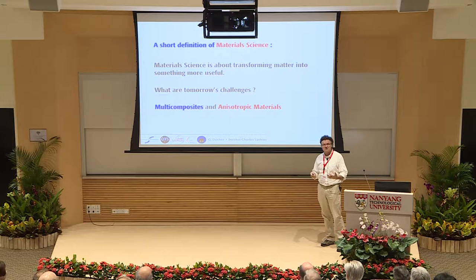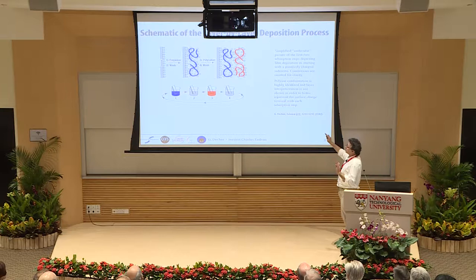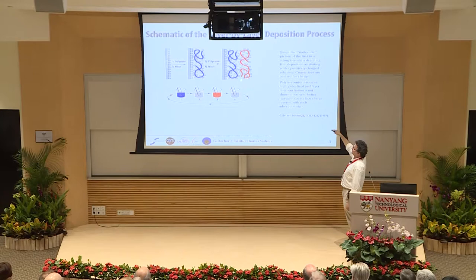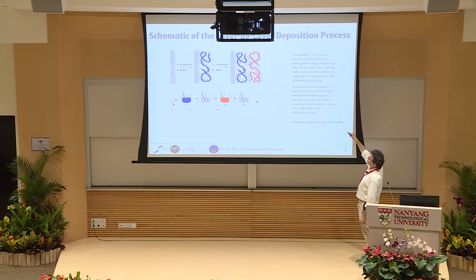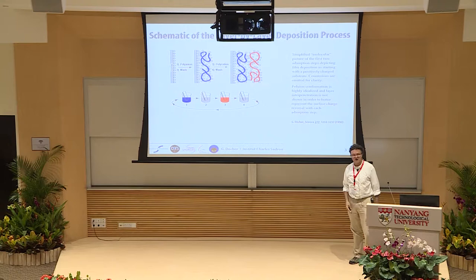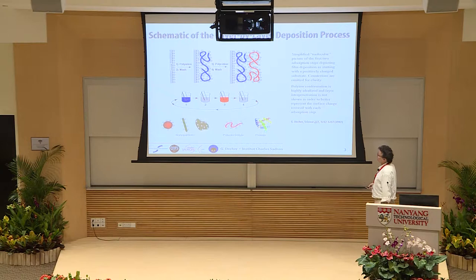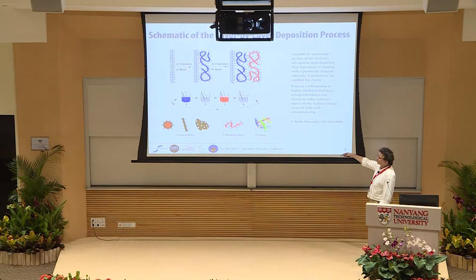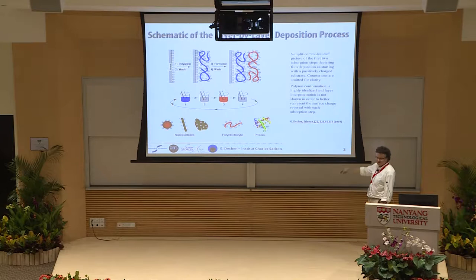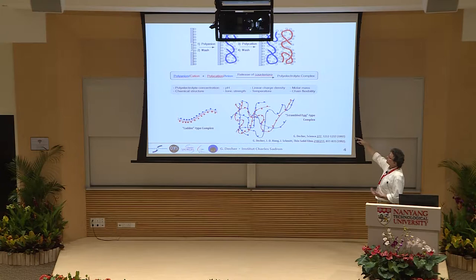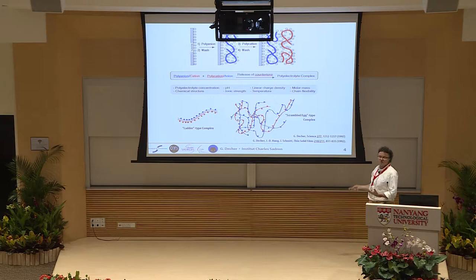This is well known: we take a charged surface, absorb an oppositely charged polyelectrolyte on top — this is a self-limiting step in thickness, about one nanometer — then wash and add the next component, repeating many times. I will show examples where we do that a thousand times. Components can be anything from the colloidal domain: nanoparticles, nanowires, nano platelets, polyelectrolytes, protein, DNA, RNA — whatever is slightly charged. We follow the rules of polyelectrolyte complex formation: polyanion plus polycation, releasing counterions to form the complex, done stepwise at an interface.